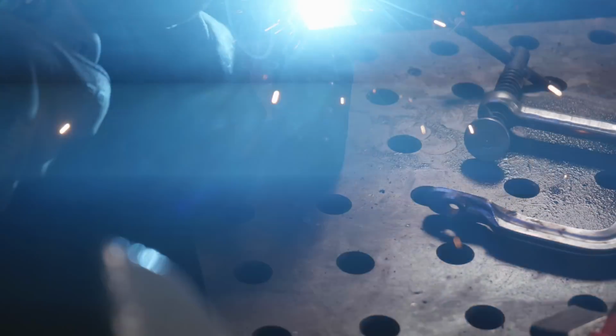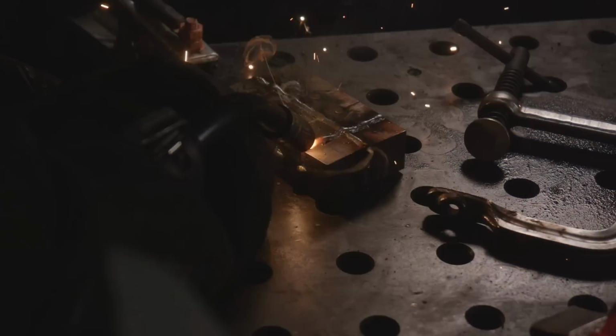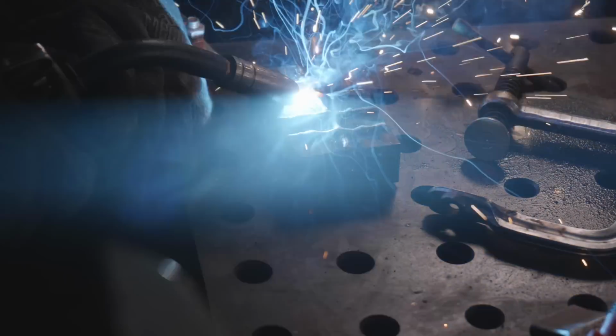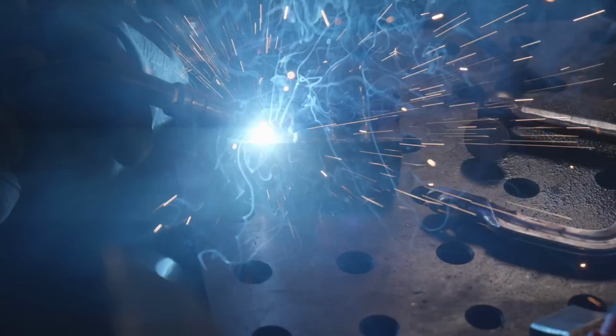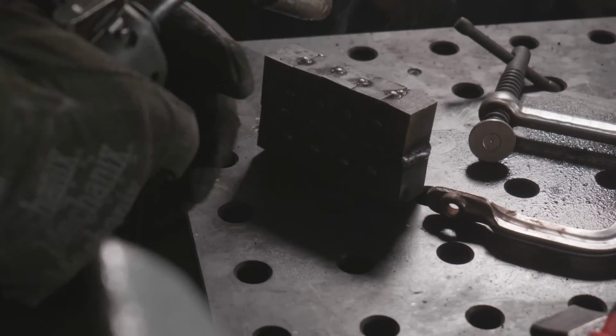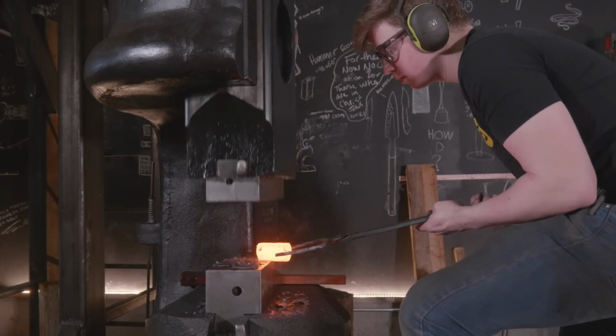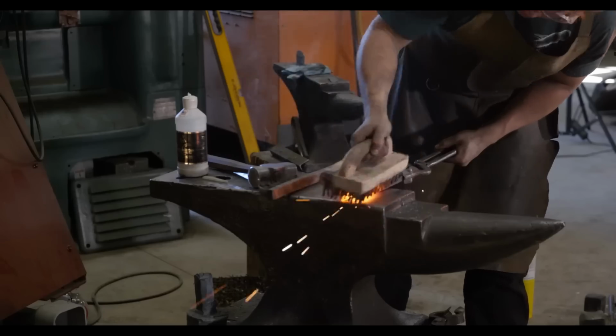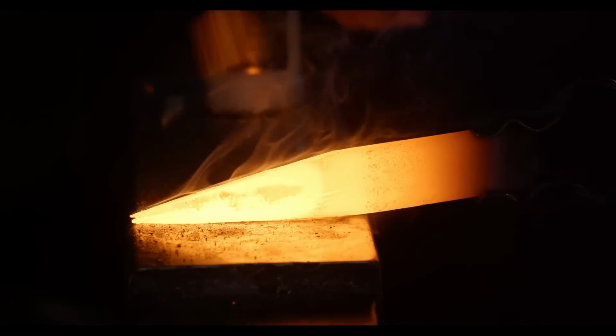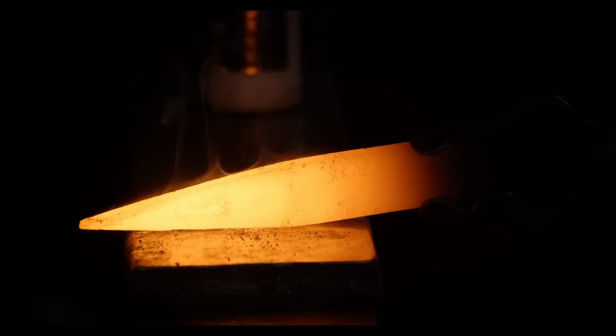Now, probably the most common method of bringing a mosaic pattern to the surface is to do what we call the tiling method, where you cut slabs off of the end of this bar and you stack them up, and you either cut them at an angle so that they can overlap with kind of a scarf joint and forge weld them together, or you can do an upset weld where you make sure that they can't go anywhere by welding around the edges or something like that. You just forge weld them flat and they expand and forge weld to each other. Also, just build a really big bar, cut a slab off of it, and then just forge it to whatever shape you want. You can also twist it, which is another really interesting way to bring a mosaic pattern to the surface because it stays really dynamic and really flowy.